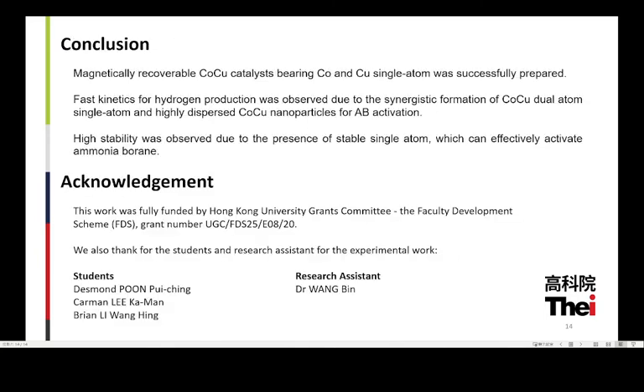In conclusion, we have successfully prepared a magnetically recoverable cobalt-copper catalyst bearing cobalt and copper single atoms. Next, due to the synergistic formation of cobalt-copper dual single atoms and highly dispersed cobalt-copper nanoparticles for ammonia borane activation, we can observe fast kinetics for hydrogen production. Also, we can observe the high stability result, which is due to the presence of stable single atoms, which can effectively activate the ammonia borane.